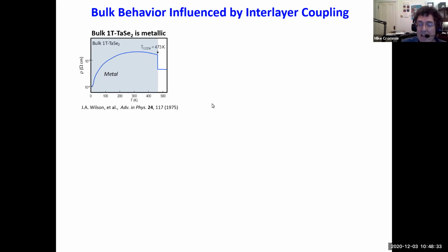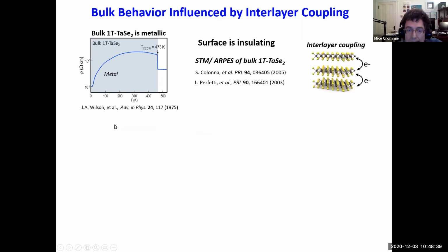But on the other hand, what surface science people have done is look at this material by STM and ARPES, and people have shown that at the surface it behaves like an insulator. So that's good. That's a little bit more like what we want. But the situation is kind of complex, and the reason it's complex is because of interlayer coupling. Here, interlayer coupling, in my opinion, is the enemy. That's the problem with this material that makes it complicated and hard to understand.